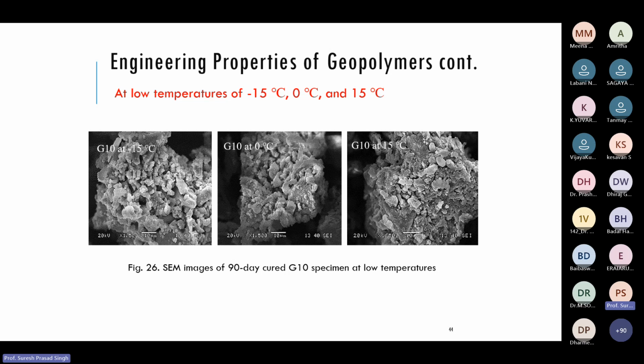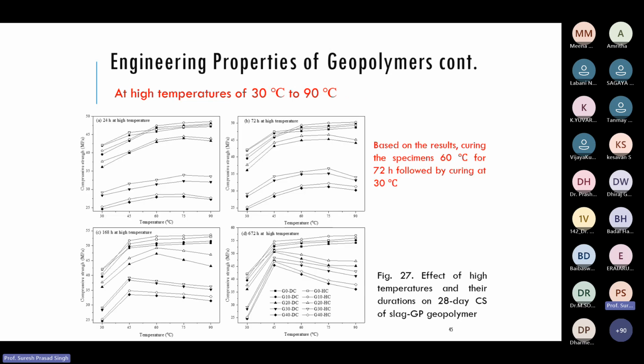This is the micro SEM image, where you can see that if you cure at very low temperature, minus 15, 0, and all these things, a lot of void space is there. This geopolymer paste is not formed, and this hardening has not set, and strength will obviously be less. Then this is the high temperature curing. These are the graphs with different initial curing temperature starting from 30, 45, 60, and 90 degrees Celsius. And as you see, as this temperature increases, the strength gain with time also increases, and the final strength will also be high.